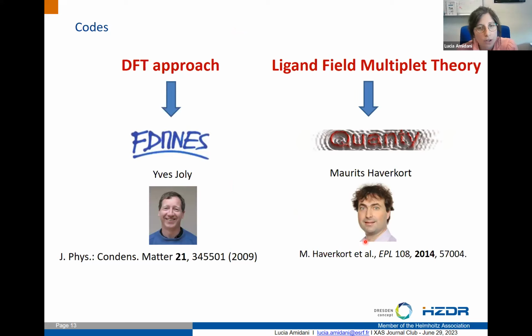We use different codes depending on the case. Personally, I mostly use FDMNES for the DFT approach, which is developed by Joly here in Grenoble. And at the moment, the code we use for the ligand field multiplet theory is Quanty, developed by Maurits Haverkort in Heidelberg.